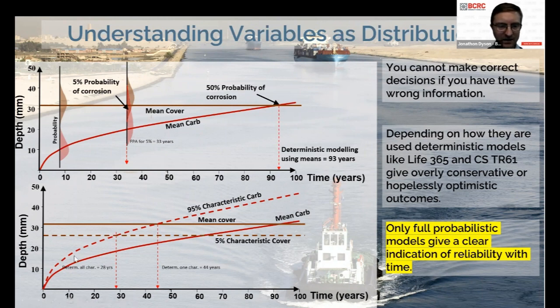So if you did that in this case, you use the characteristic cover and you used the characteristic carbonation, 95% carbonation. In a deterministic model, that was giving us 28 years remaining service life, which is actually less than what the full probabilistic analysis did. So that's an example of deterministic modeling actually being overly conservative. So deterministic modeling can be sometimes overly conservative or sometimes hopelessly optimistic. Basically, it's just not as accurate as full probabilistic analysis.